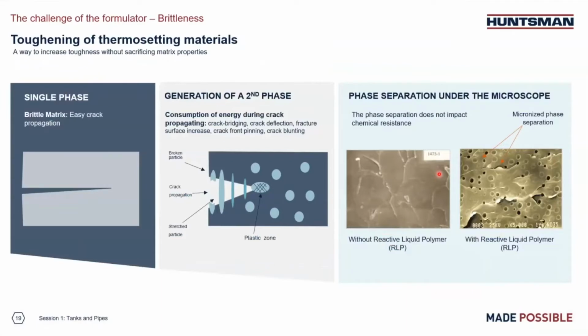So this slide explains why and how the toughener works. Without the toughener in the system, the polymer matrix is just one single phase, so when a crack happens, it will very easily propagate all the way through. By introducing the toughener into the system, because of its incompatibility, we introduce a second phase. This second phase is made of rubbers, so it's very flexible material. When a crack happens, it will absorb the energy and stop further propagation. The two SEM images here on the right basically show we can disperse this micronized reactive polymer into the matrix to improve the overall system toughness.